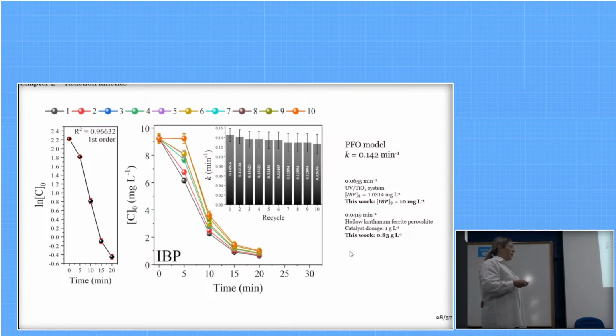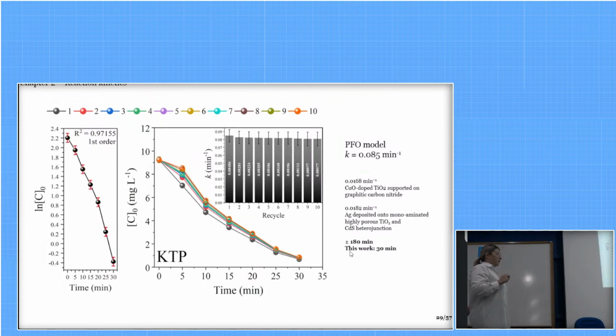The recyclability for ibuprofen degradation was also high, with no significant decrease in the kinetic rate observed in up to 10 cycles. For ketoprofen, the outcome also fit the first order model, and the recyclability was even more stable for this compound, and the total mineralization was reached within 30 minutes, while the literature reports the need for approximately 180 minutes using even the so-called advanced catalysts, such as the ones doped with titanium and using graphitic carbon nitride, or catalysts with higher cost, such as using silver.